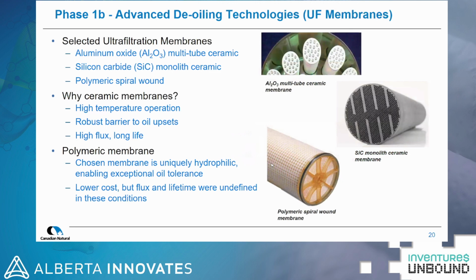The polymeric membrane, this specific one was chosen because it's uniquely hydrophilic. So we were expecting very strong oil tolerance. It's a lower cost. It could provide a lower cost solution. But in this application, the flux and the lifetime of the element were big question marks.